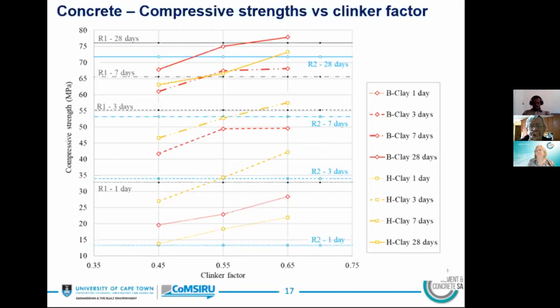Now you can see for the LC3 mixes with B clay, from 3 days onward, there is little gain, almost no gain of strength, moving from 0.55 to 0.65 clinker factor. Now this means that in this system, you do not really need the amount of clinker above 55%. Unlike LC3 mixes with H clay, where the gain of strength also depends on the clinker factor, at least up to 0.65, 65%.